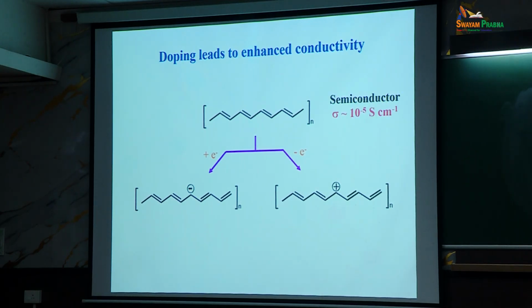Then the conductivity changes. From here 10 power minus 5, it goes to 10 to the power plus 4. Almost 9 orders of magnitude. So this is an amazing thing. That means you have a polymer now which is conducting. So this is what is called conducting polymer. This polyacetylene is not very air stable, but people developed many other polymers.